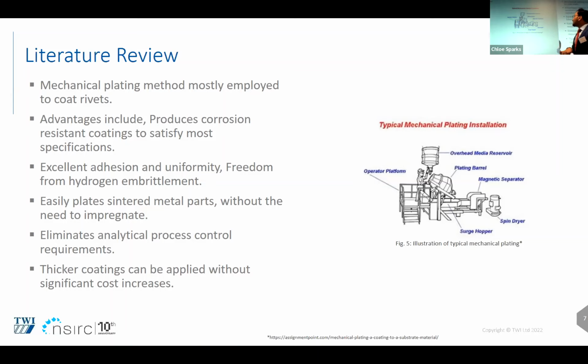And the plating barrel contains glass beads that hit the surface of the rivet and deposit the coating by using mechanical forces on the rivet surface. The coating thickness that we develop from this mechanical plating of rivets is usually 8 to 12 micrometers. And the rivets are processed through this belt, separated through a magnetic separator, and dried for further processing.